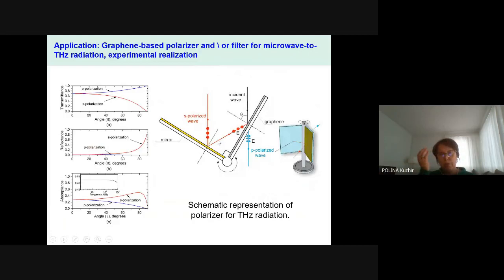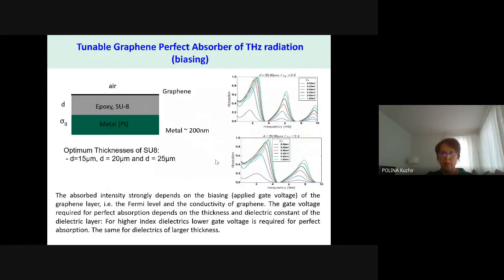So we propose to use this interesting property to fabricate a polarizer for microwave and terahertz radiation based on graphene. When the radiation comes onto the graphene plane on top of a thin dielectric, you could collect the p-polarized wave here, and after the mirror, you could collect the S-polarized wave here. So this is really a good and very effective polarizer for electromagnetic waves of terahertz and microwave radiation.